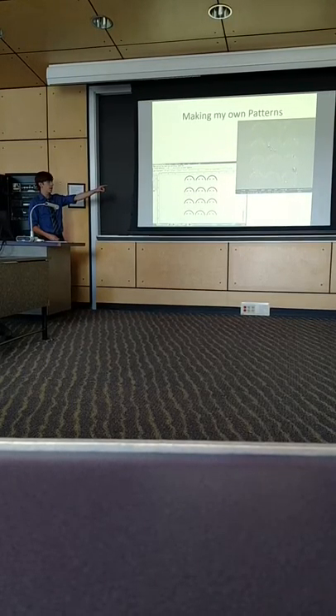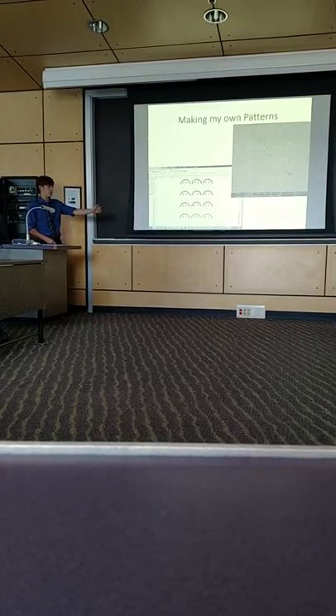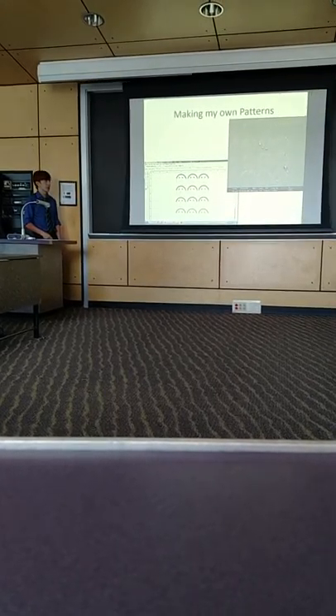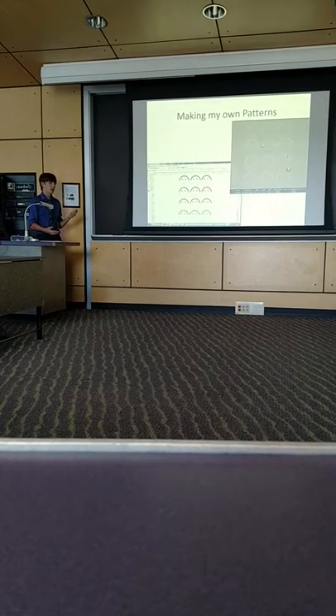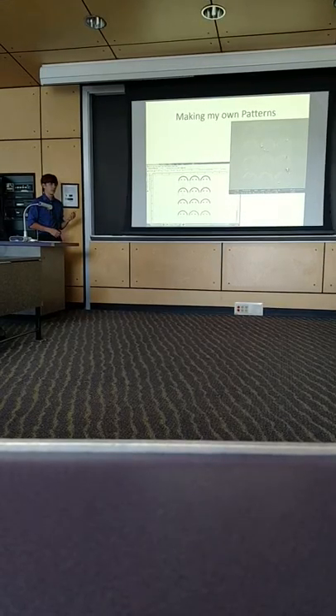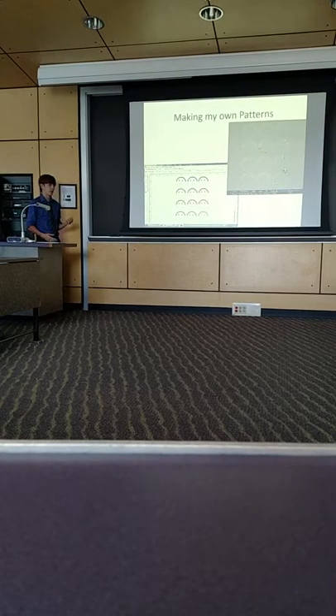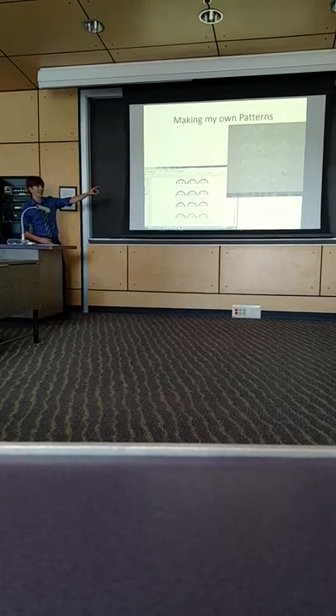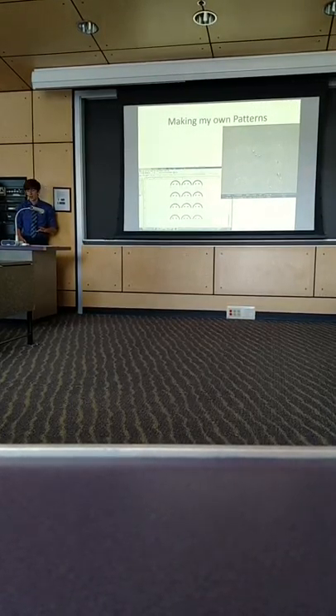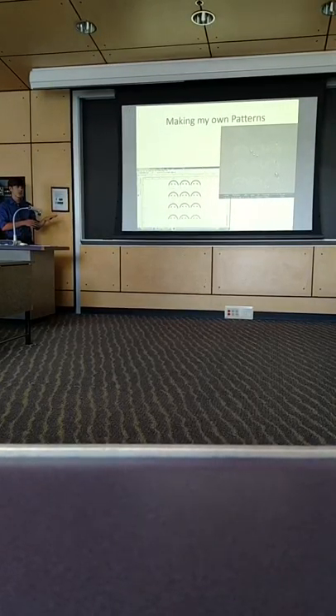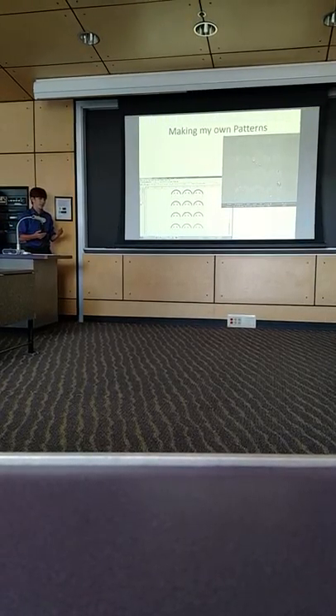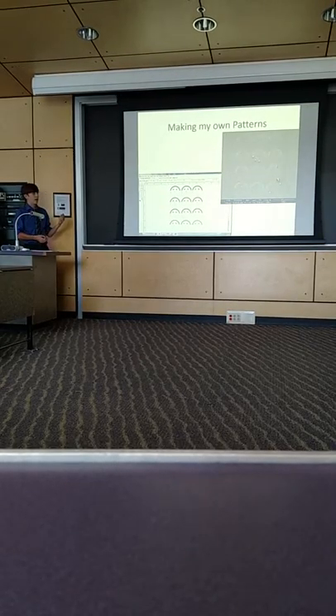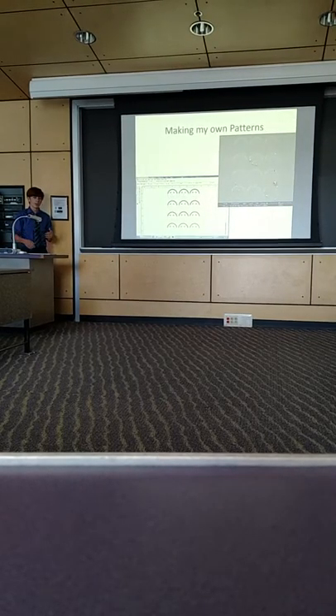So, that was my first project to try to figure out why that was happening. And then, I also tried to make my own CAD models to do my own lithography. These are what they're supposed to look like, little smiley faces or something. And that's a dose array. I believe starting at the top left hand, it would be 1.8 nanocoulombs per square centimeter. And then, in the bottom right-hand corner, it would be around 4 nanocoulombs per square centimeter. You'd have an array because sometimes, if you had a large enough array, some things would get better resolution than with finer lines or larger lines. And then, print faster with a smaller dwell time or nanocoulombs per square centimeter. But, that is what I ended up getting, which is nothing here what I intended to draw.